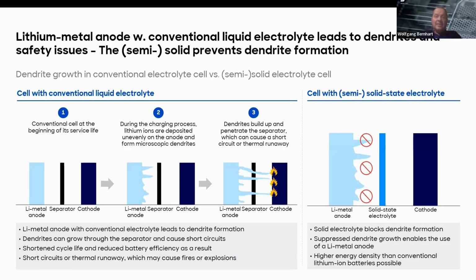So with conventional liquid electrolytes, during the charging process, lithium ions are deposited unevenly on the anode and can form microscopic dendrites. And if those dendrites build up and penetrate the separator, you have a short circuit or a thermal runaway, and you have all these events that you don't want. So having a lithium metal anode with a conventional electrolyte can lead, or will almost certainly lead, to dendrite formation that grow through, and that means you have a short cycle life, you have reduced battery efficiency, and you have the risk of short circuits, which may cause fires or explosions. So you use that solid state electrolyte to block the dendrite formation, and the suppressed dendrite growth enables the use of the lithium metal anode, and that again allows to increase significantly the energy density.